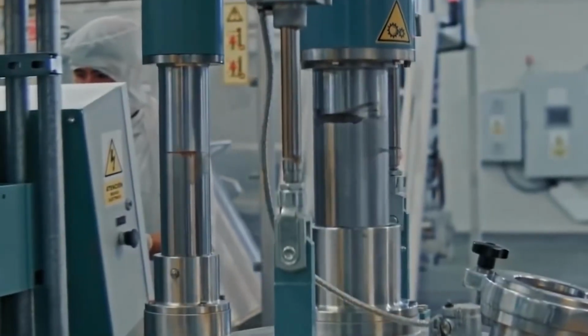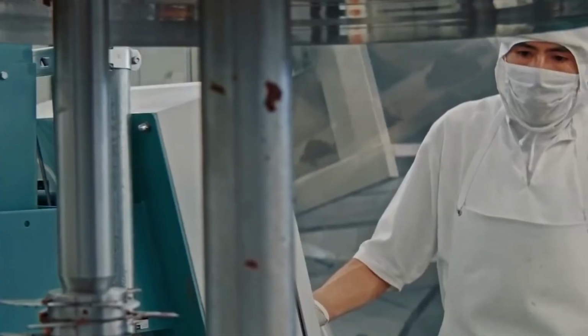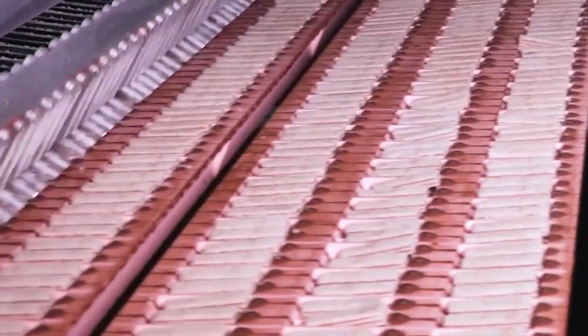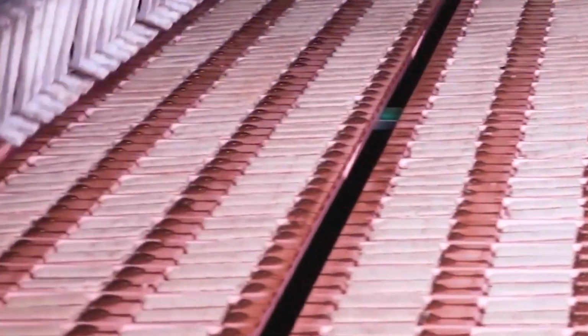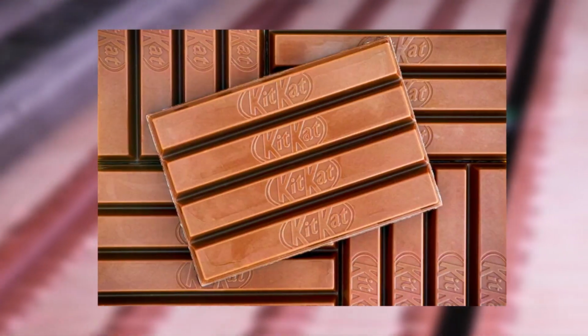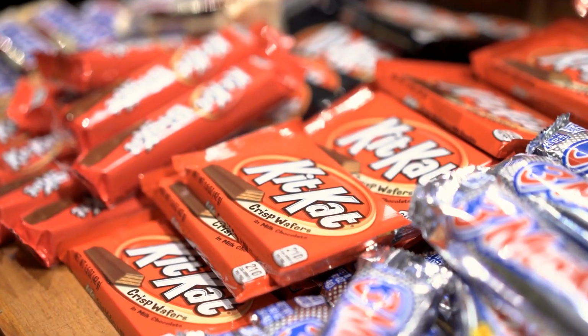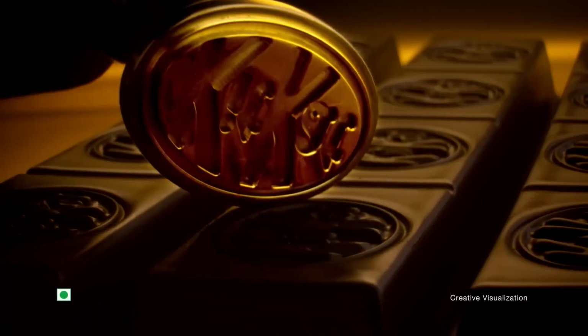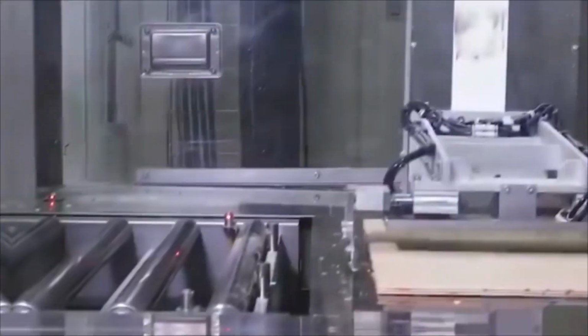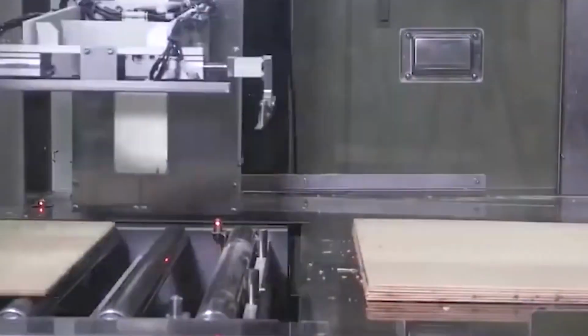Precision reaches its peak during cutting. Using diamond-edged blades oscillating at 10,000 strokes per minute, automated saws slice the wafer sheets into fingers with plus or minus 0.1 millimeter tolerance. For a 4-finger KitKat, this means each of the 3 grooves between fingers must be 1.8 millimeters wide. Any wider, and the chocolate coating would pool. Any narrower, the snap would falter.